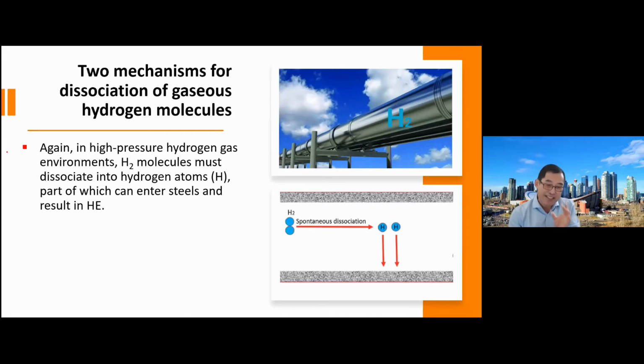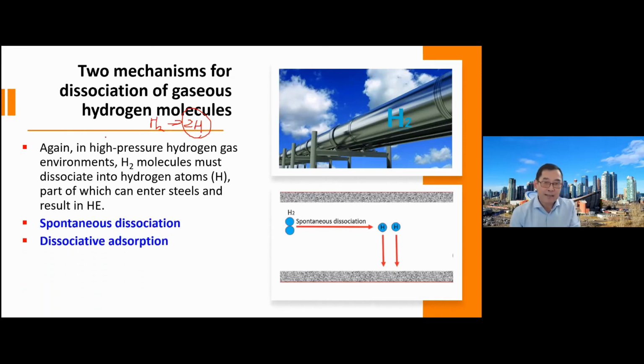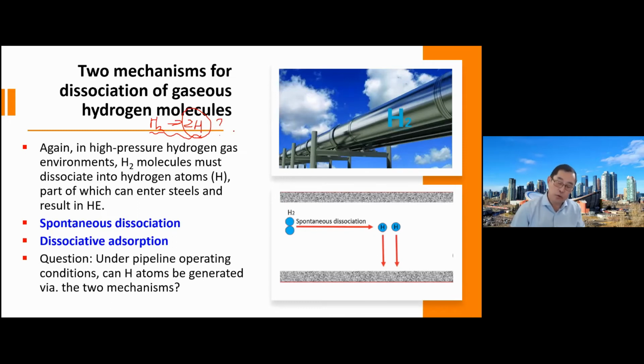If your assessment tells you hydrogen is present in the gas phase, then as I just mentioned, for hydrogen to go into the steel from the gas phase, the step must be H2 decomposing into H. This is a very critical condition for hydrogen atom generation. Then, under the pipeline condition, will this reaction really happen? So you need to do an assessment. In general, for the gas phase H2 to change into hydrogen atoms H, there are two mechanisms. The first one is spontaneous dissociation.